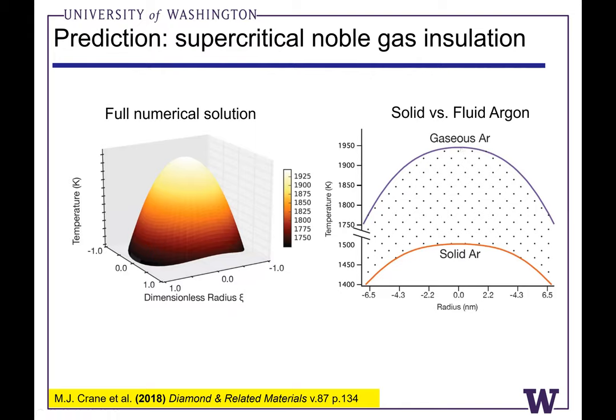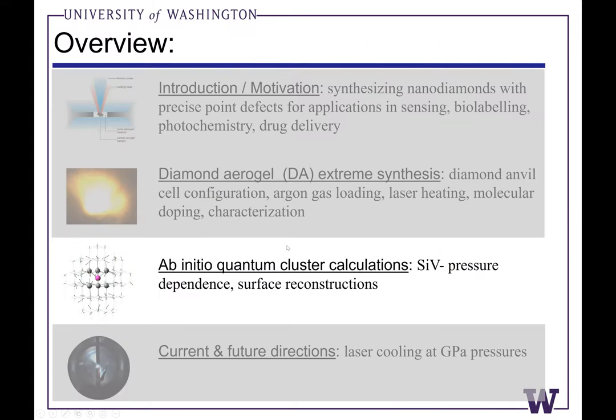It's always awkward to talk about it: it's not melting, it's not a solid to liquid phase transition, it's a solid to supercritical fluid phase transition with no surface tension. So these atoms are really able to move. There's really a very low surface energy between the supercritical fluid phase and the solid material.